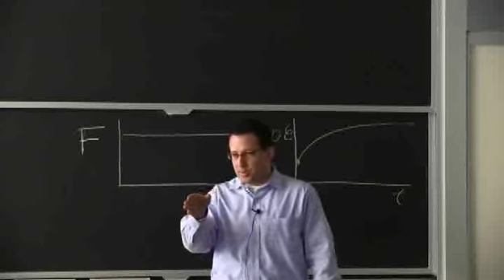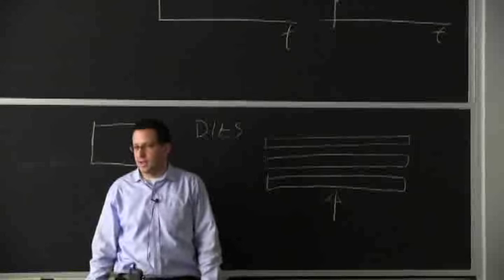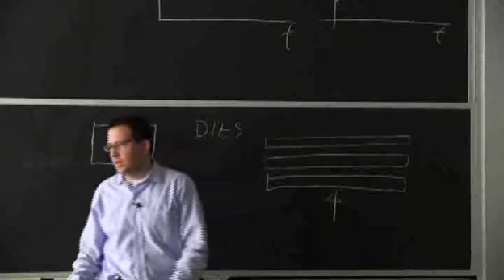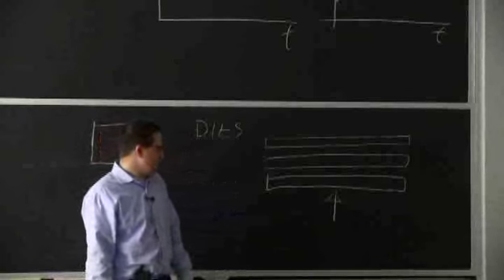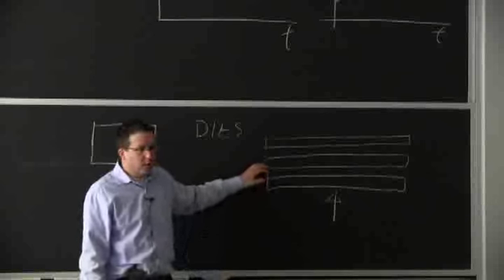The polymer really has very long chains, and you end up with chains that are longer in this direction than in that direction. So when I try to propagate a crack through a material that's essentially a line, the energy required will be much higher to do it this way, perpendicular to the chains, than if I try to go in between them. And that's why there's no question that it's always going to be a longitudinal crack, unfortunately, unless there's really something about the joining, something about local loads, that creates a condition where you crack transverse. So you're going to crack in that direction.